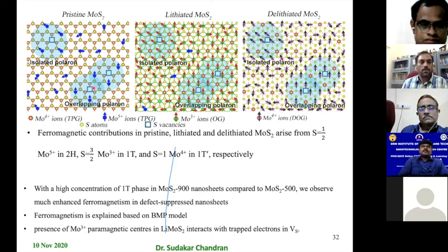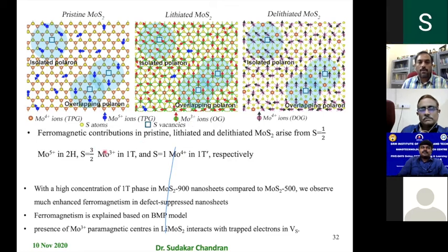So when you have sufficient concentration of defect sites and also spins, you have a long range interaction, and therefore ferromagnetism is seen. Like in this case, you have moly in a 3+ state, which gives rise to 3 unpaired electrons when it is present in the octahedral site. If it is not a part of this magnetic polaron, they're all just paramagnetic sites. But if they are overlapping, they're all oriented in the same direction, as schematically shown. All the spins within the circles are oriented in the same direction. So the overlapping magnetic polarons will have spins oriented in the same direction. And if this is permeating because of the concentration of the defects, then you will have long range order. And that's when you happen to see ferromagnetic-like behavior.